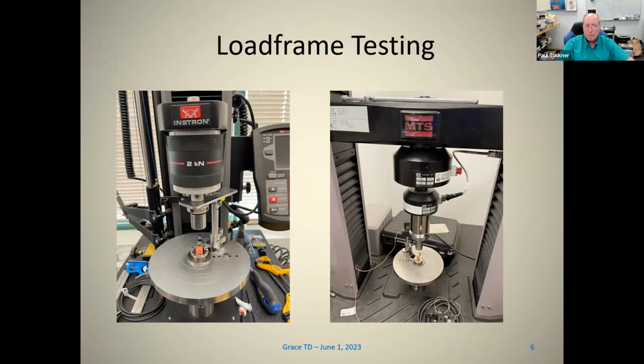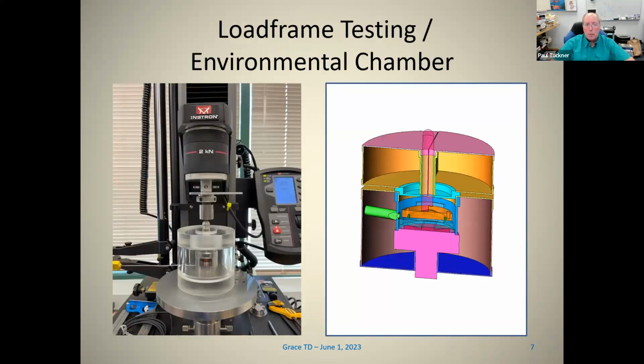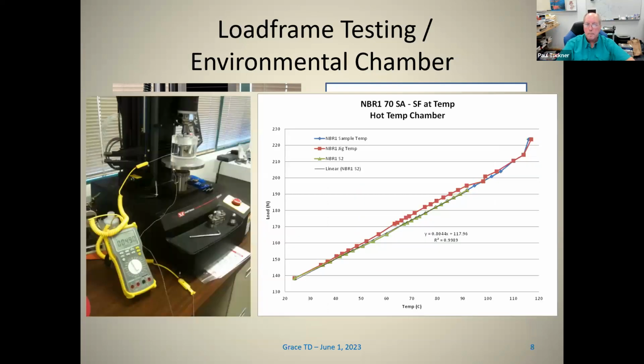If you had an environmental chamber around those configurations, you could test at different temperatures too. Here's a case where I've developed two small environmental chambers. One is a high temperature chamber where you can take a jig and put it in this insulated quartz chamber, and do load deflection curves as it's cooling down - I'll show that in a second. The other is a controlled temperature chamber with conditioned air fed in, where you can check the sealing force on the seal in that configuration, and also use it to check for leakage, which I'll talk about in a second.